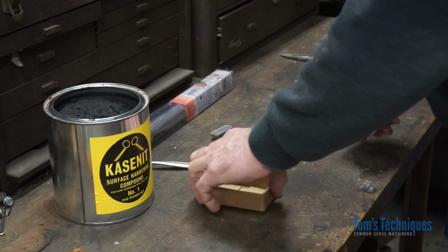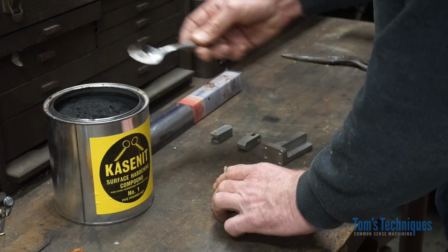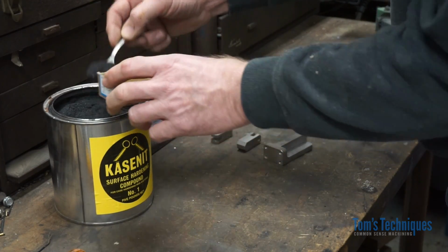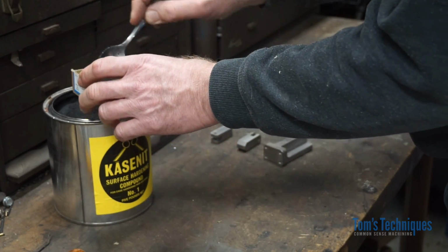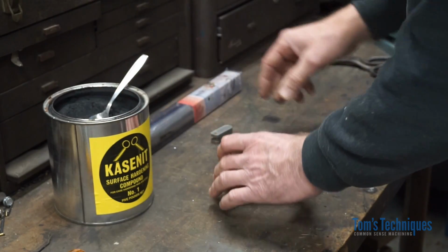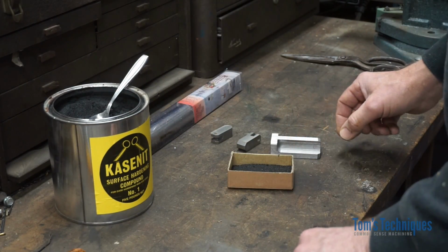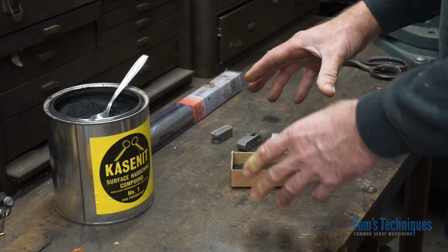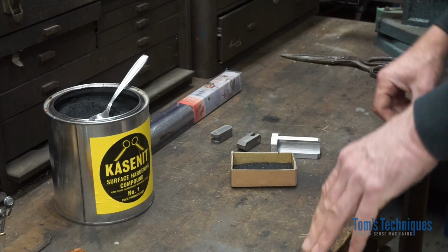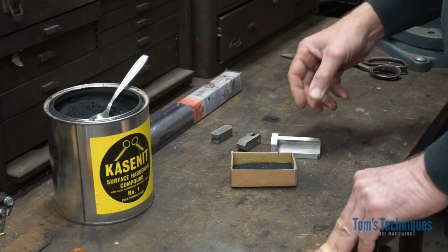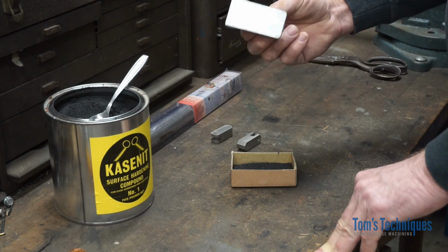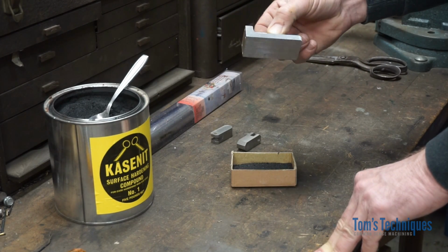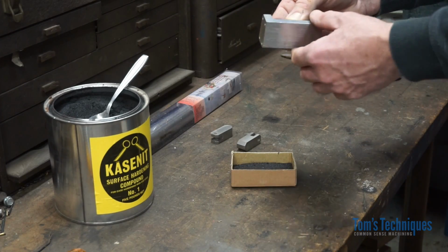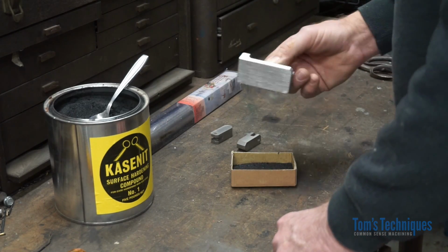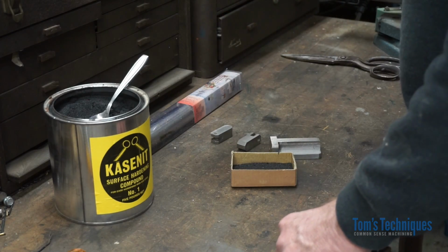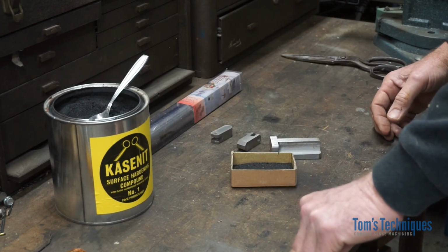So first thing we need to do is put some of this stuff in. I like to use a box just to help hold everything together. It not only holds the parts together, but whenever you do this process, you do it inside an airtight container. The reason is that if there's oxygen exposed to the parts at high temperature, they oxidize and it makes the surface very rough. So if you want to keep a nice looking part, you have to do it in a low oxygen atmosphere.